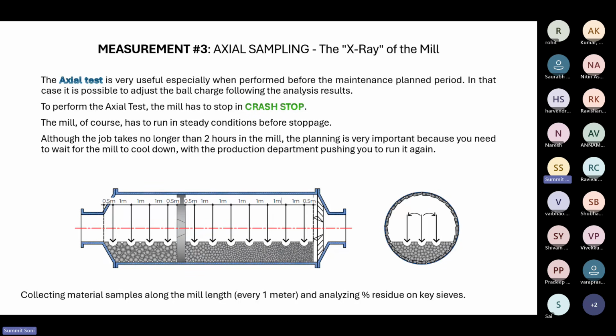Second thing is, from 80 to 72, what has changed? Because the mill TPH will reduce. Let's say it has gone down from 80 to 72. What has changed in the mill, which I knew during my crash stop on January 1st? I did a crash stop in the first week of January. This was the status of the mill. This was the filling degree. This was the piece weight analysis. All those things I know now. Come 31st of May, what has changed in my mill?